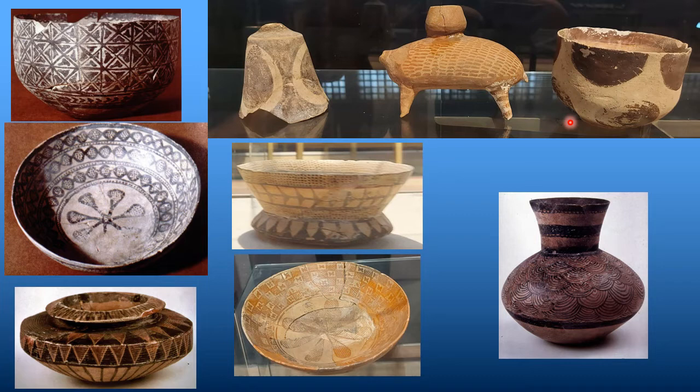And so what you do is you levigate it, as we call it, which is basically sticking it in a basin with water and mixing it up and letting the fine clay particles float or sink to the bottom. Sorry, the heavier clay particles sink to the bottom. The lighter clay particles will come to the top, and you basically can scoop out the lighter clay stuff to make really fine pottery. And so clearly they knew the process, and they were spending a lot of time doing this.